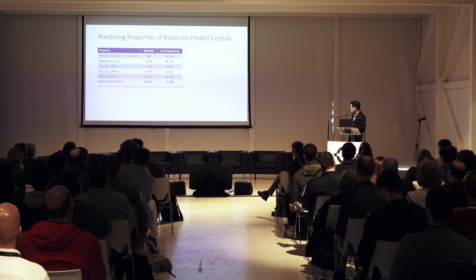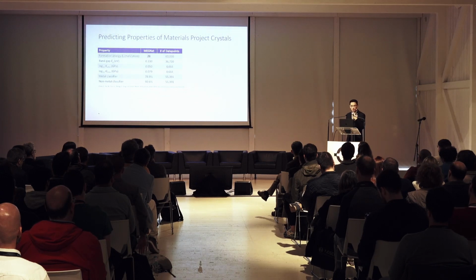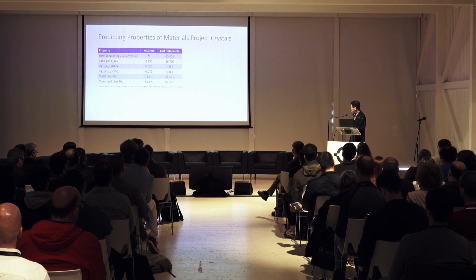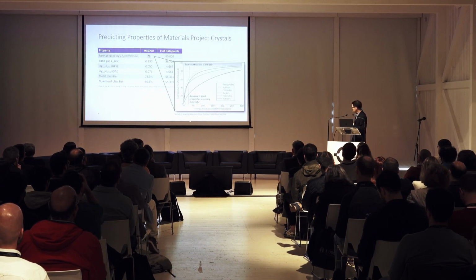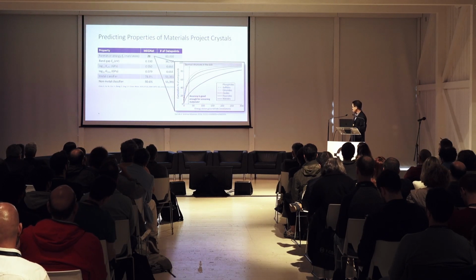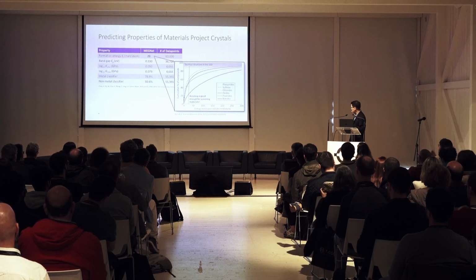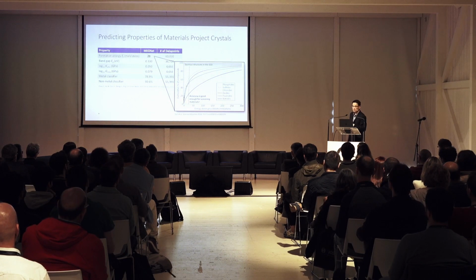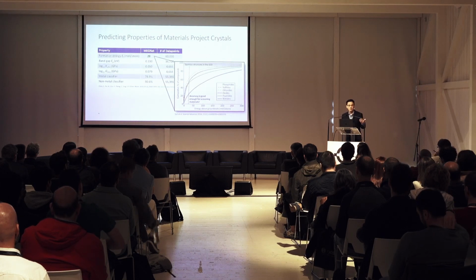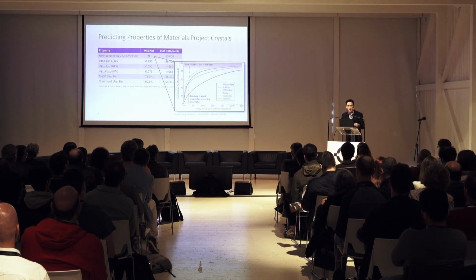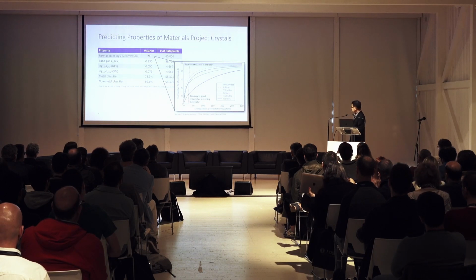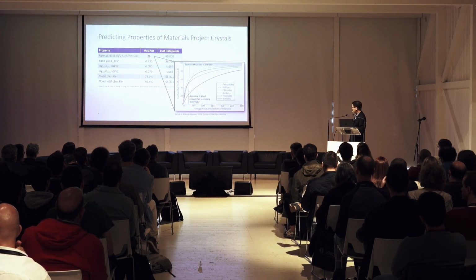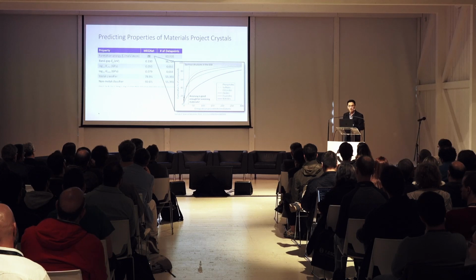answer a few questions. First of all, giving you these numbers doesn't really help, in the sense that you don't know whether these are accurate enough for you to actually do materials design. I want to put this number in context, right? There's a study that was done by my colleague Wenhao Sun back in 2016, where he looked at the energy above hull for all the crystals in the Inorganic Crystal Structure Database. In other words, materials that mostly have been synthesized experimentally somewhere. What he found was that about 80 to 90% of the crystal structures fall within about 100 milli-electron-volt per atom above the convex hull, right?